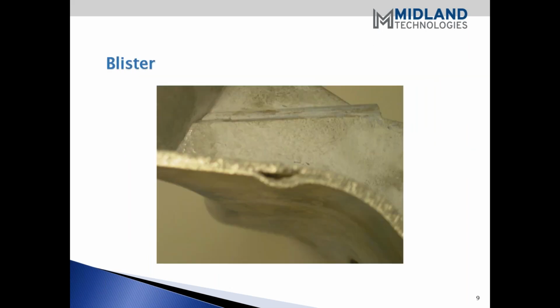Now this is a cross-section area through, not a real clear picture, but it gives you the idea of a blister that's occurred in this particular casting. And of course, this blister was formed with air trapped in the metal, and in this instance, as the casting cools, that air expands if the wall thickness doesn't have enough integrity to resist the air being compressed and expanding with the softer metal. Usually this will happen. I've seen it happen. You pull the casting out of the machine and that blister forms. You can watch it form right as it's laying on the conveyor.